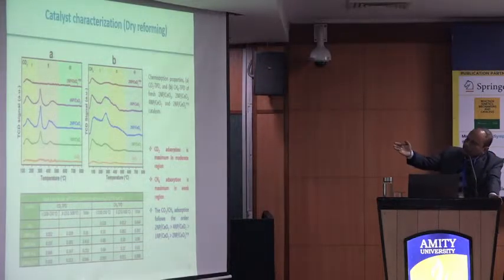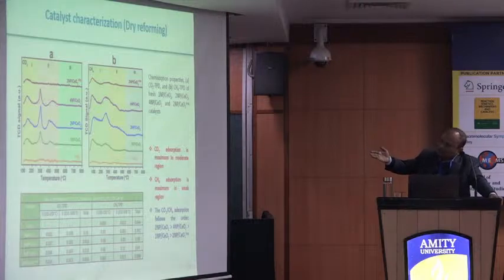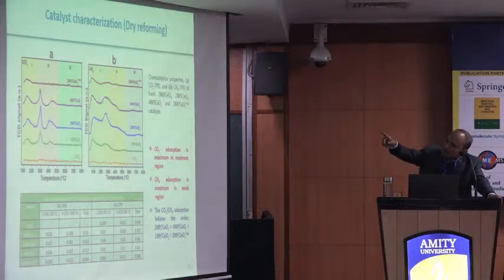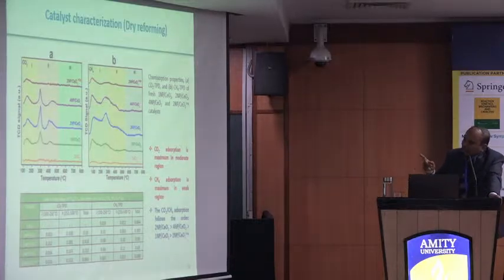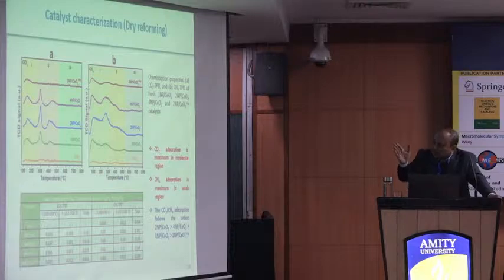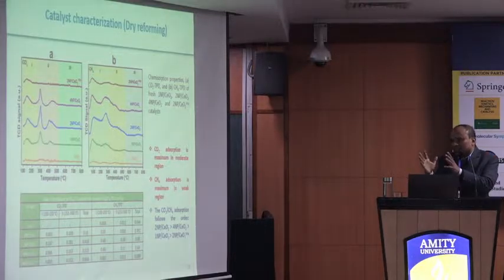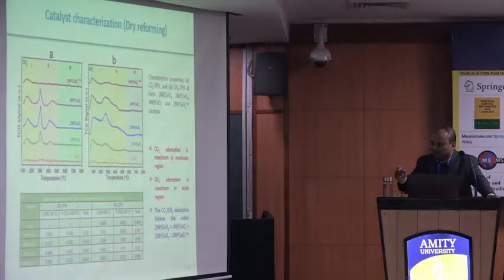Also, we have done some adsorption study, CO2 adsorption and methane adsorption. You can see here that CO2 adsorption is maximum in the moderate region below 500 degrees centigrade, and also methane adsorption is maximum in the weaker region. That means the catalyst is very active for methane and CO2 adsorption for this reaction.